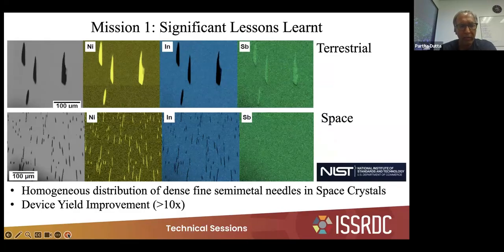This is the third-party validation, courtesy NIST, these pictures, and this summarizes the significant differences in terrestrial crystals that were grown under the same conditions in the ground control system in the SUBSA furnace at Redwire, and then the crystal that was grown in ISS. And I don't have to really talk more. You can see the differences in the morphology of the crystals that were grown terrestrially and in space. And the key thing here I would like to highlight is that the distribution of the microstructure, which is the semi-metal needles, they are homogeneously distributed in the space-grown crystals, and the size distributions were very different. And this directly translates into a device yield improvement of more than 10x, and that's something very, very significant. This material has been used commercially for many applications for the last 60 years. And this is the first time we are seeing such high improvement in device yield from space-grown materials. Next slide.